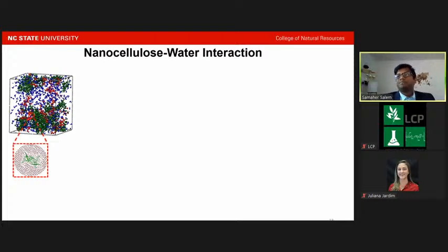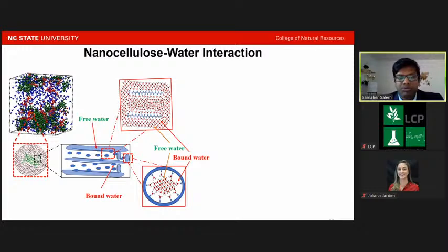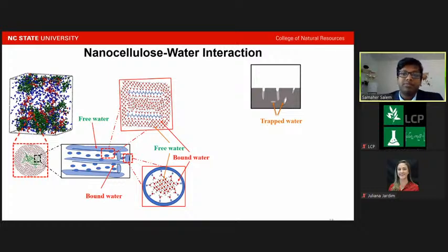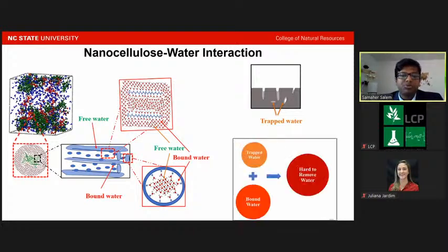So we wanted to find how the nanocellulose and water interact and how the water is really affecting the reactivity of the cellulose. We know that there are two types of water, the free water and the bound water. The schematic shows that the free water is the bulk water, and the bound water is the water that has formed hydrogen bonds or is really adjacent to the first or second surface of the cellulose hydroxyl. And there is another kind of water, the trapped water, which is formed when you try to dry the sample, and a few water molecules get trapped inside the matrix. So the trapped water and the bound water are hard to remove.